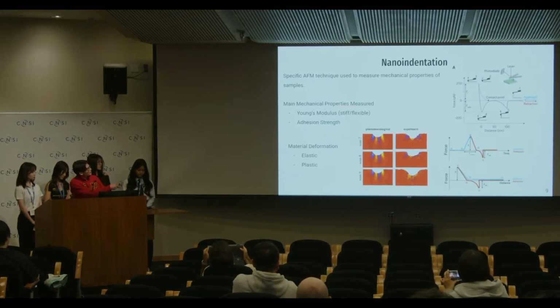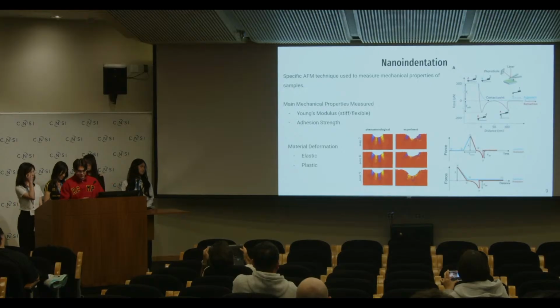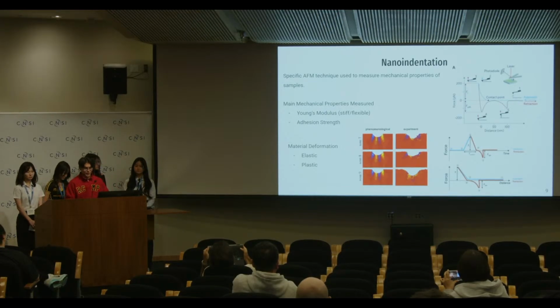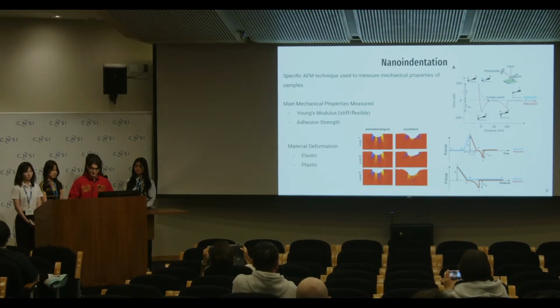And then here in Figure A, you can see an example force distance curve where at point 1, the probe is away from the sample, so there's no force being applied. At point 2, that's when the probe starts to contact the sample, and then that measures the Young's modulus, or the stiffness.